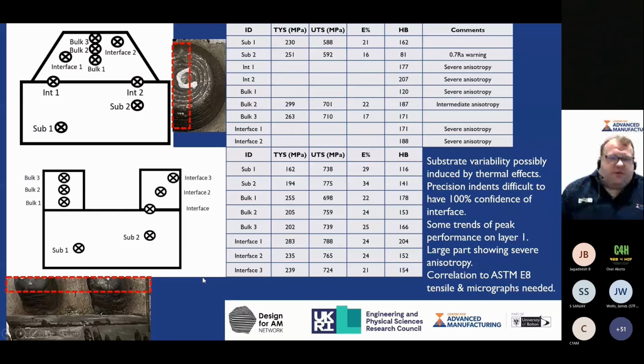So we managed to get some data to look at the substrate versus the interface between substrate and weld, and weld one, if you like, the bulk material, and then the interface. So again, looking at the weld performance. The idea with WAAM is that the interface should be as strong or potentially stronger than the bulk material. The use of the substrate is a key part of minimizing material waste, so again, we should have similar performance.